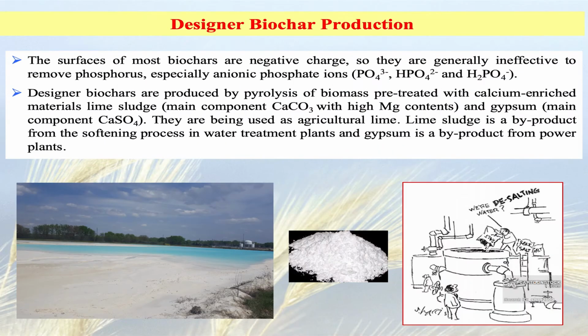Since the biochar surface is negative, they are not efficient to capture or absorb dissolved phosphorus, because phosphate is mostly an anion, unlike ammonium ions. So that's why we thought, can we make some designed biochar? They can capture this anion material as well, like dissolved phosphorus. So we're using some lime sludge or some gypsum to pre-treat the biomass to make designed biochar. Lime sludge is usually used in the agriculture field for liming. Lime sludge is a byproduct from the drinking water plant. In drinking water treatment, they use limestone to soften the water. So this is good. This is a byproduct we're using to make our designed biochar.